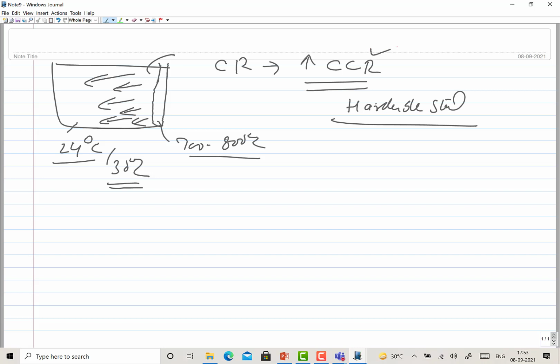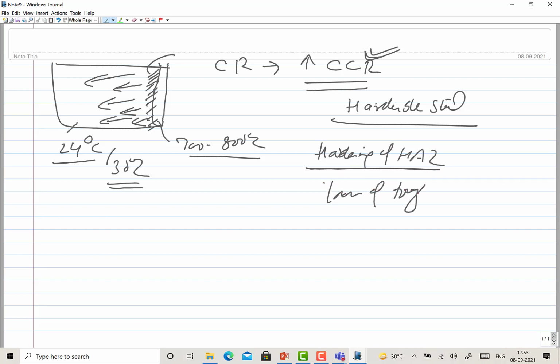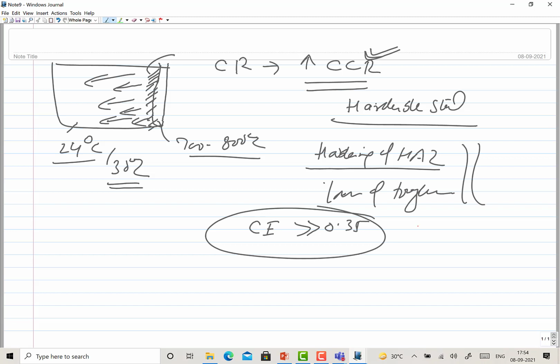So hardenable steels experiencing a cooling rate greater than the critical cooling rate in the vicinity of the weld interface or joint interface, then certainly you can expect hardening of the HAZ. So hardening and embrittlement or loss of toughness, all these can be the issues in case of friction welding of hardenable steel, and therefore any steel having a carbon equivalent greater than 0.3 or 0.35, you can say, will need some kind of precaution to restore the properties, because this will lead to embrittlement and hardening of the heat affected zone.